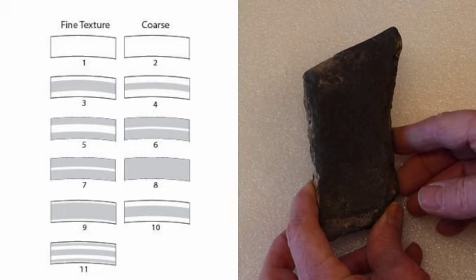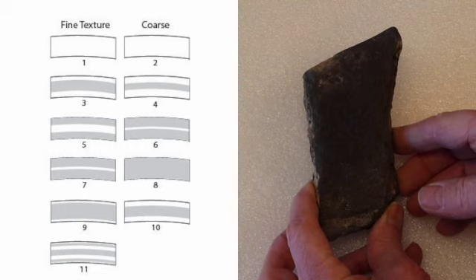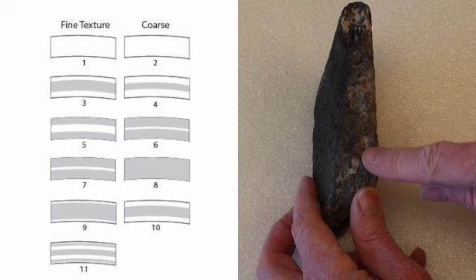This sherd has a very thin oxidized layer on the exterior, but is otherwise reduced all the way through. Most likely it was originally fired in a reducing atmosphere, but then re-fired in an oxidizing one after the application of an exterior slip.